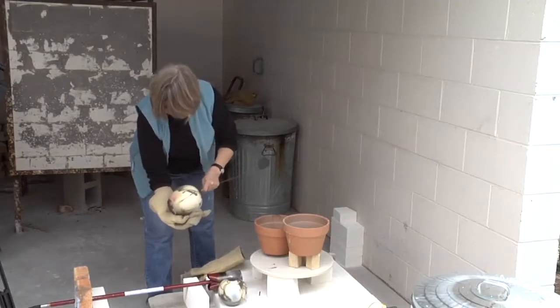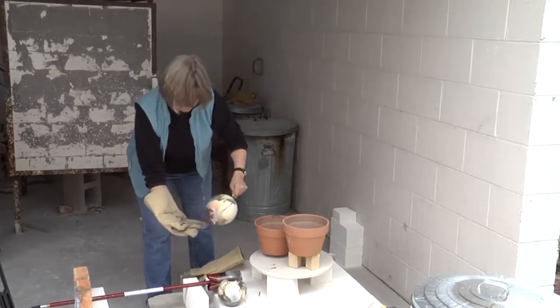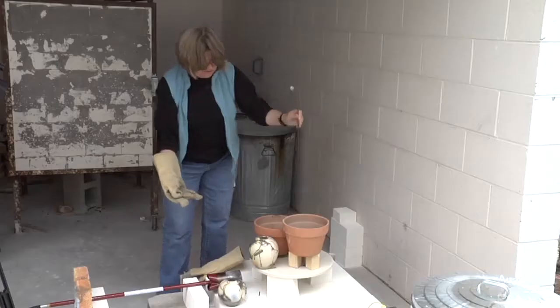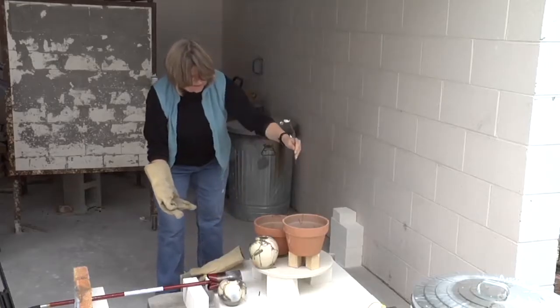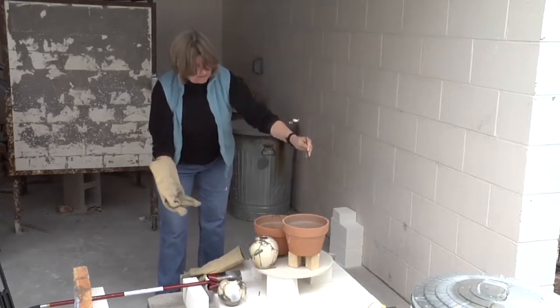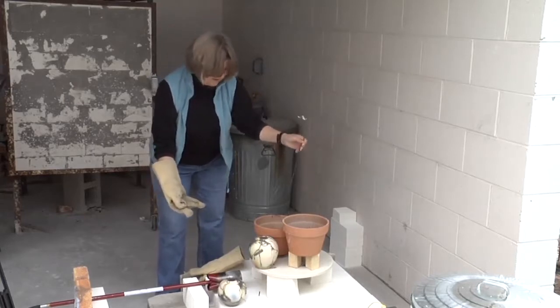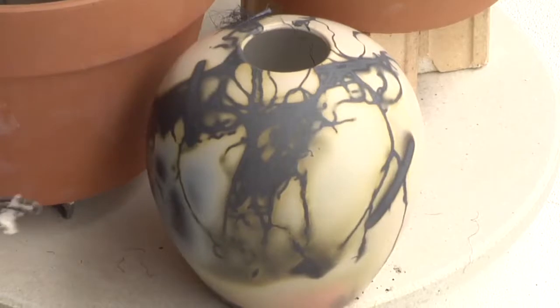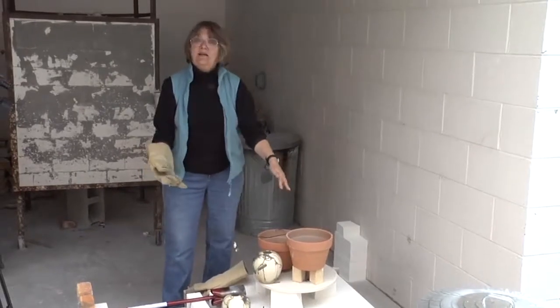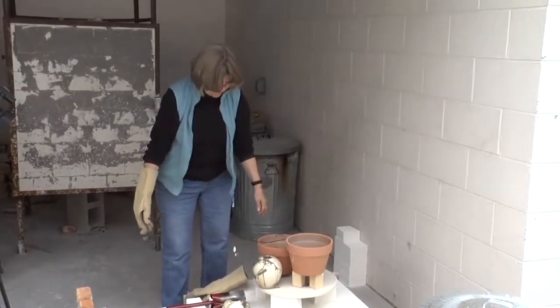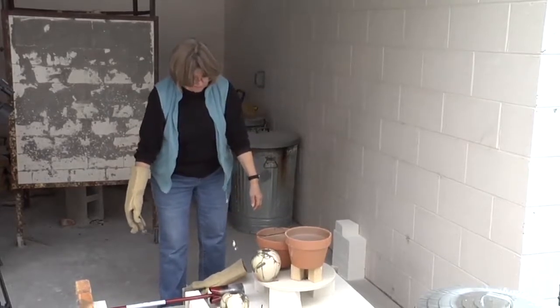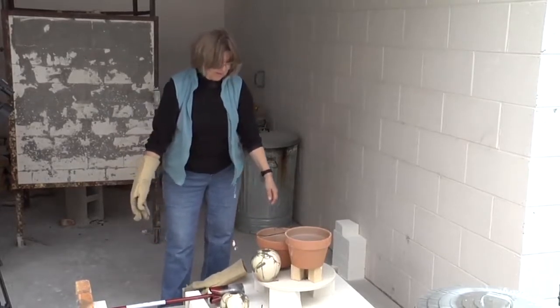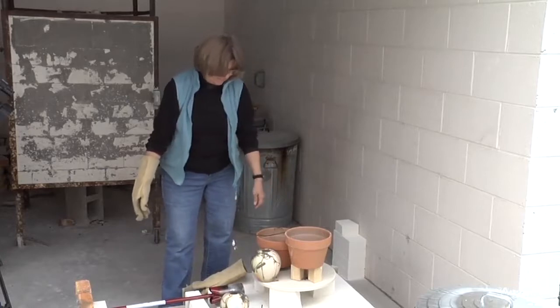And it looks pretty good. I like all the bright colors down below. Great colors. So I'm pretty happy with that. I really like the green and the peach and the black together. There's a slight crack in this sagger, but it could be used again. Maybe put a little paper clay over it just to seal it up better. I make my own saggers out of raku clay, and they've lasted quite a while. So it's worth the time and energy if you can do it, but if you can't, these work just fine.